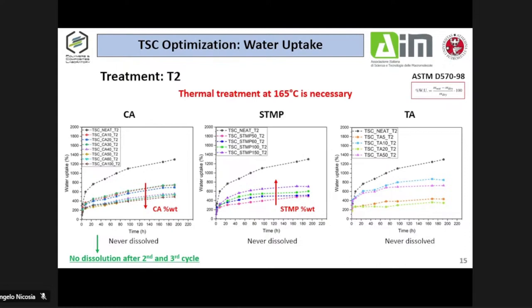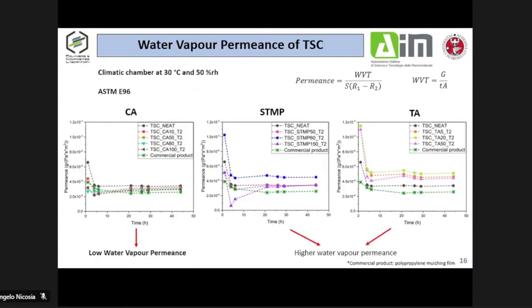And so from this test, we can say that the thermal treatment is necessary. And finally, we also measured the water permeance, which is the water vapor permeance, the permeability normalized on the thickness. We compared with a commercial product, a commercial polypropylene mulching film, and also in this case we found good results for the citric acid, which are very similar to the commercial product.